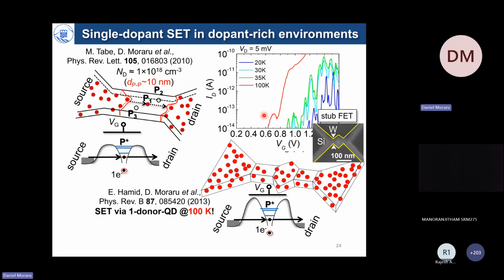What you should notice here, however, is that this is not an easy current to catch. Please note the current level of this kind of peak embedded into an otherwise FET on-off switch current. The current level is just a few tens of femtoamps. So in order to detect this kind of currents, we should have the equipment and also the stability of a measurement system and the high quality of the devices. Otherwise, this is embedded completely in the noise level.